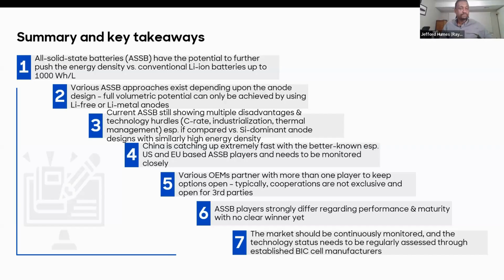Thank you. Michael. Yeah, sorry, one more question. I'm still thinking dendrites, and in reality, the rule of thumb for lithium is 1 milliamp per square centimeter current density. If you exceed this, there is high probability of dendrites growing. Obviously, if you have a very, very low thickness of lithium, you can play with C rate. If it's very thin, you can get a very large number, but still 1 milliamp per square centimeter, and it is defined by exchange current density. This is a term which is used in electrochemistry.